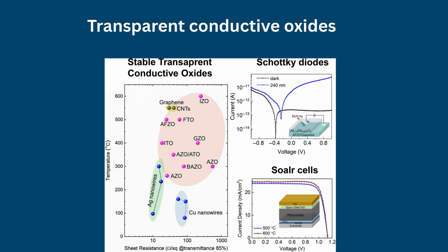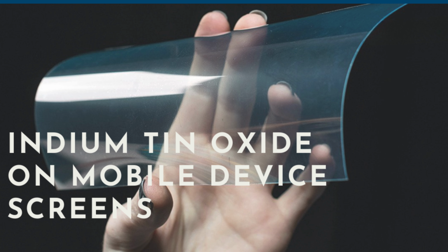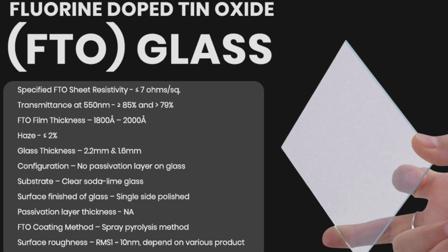To address cost and mechanical limitations, alternative transparent electrodes such as silver nanowires, graphene composites, cadmium tin oxide, and biomass-derived conductors have been developed. For instance, Ag nanowire graphene hybrid electrodes have demonstrated PCEs exceeding 15% with improved thermal and environmental stability. Flexible bio-derived electrodes have also enabled mechanically robust PSCs with high bendability.